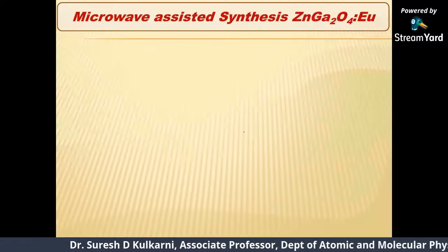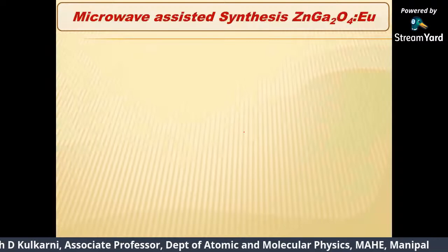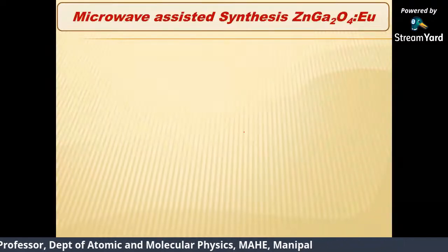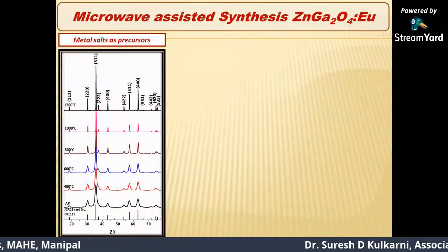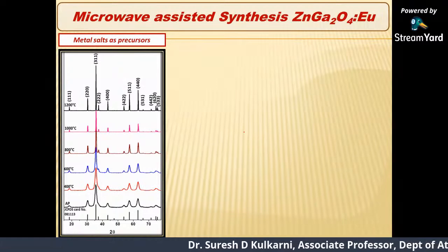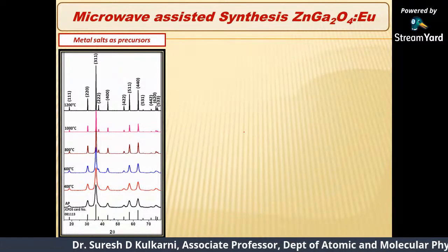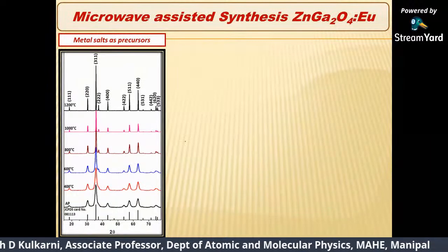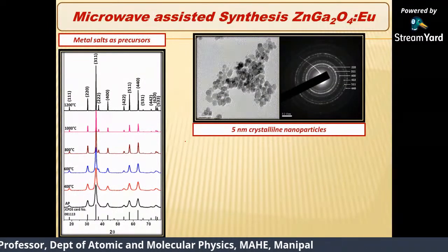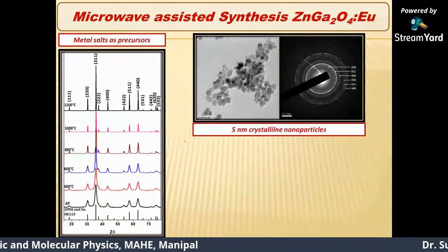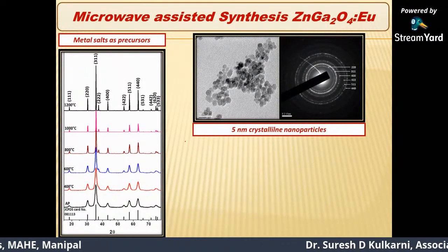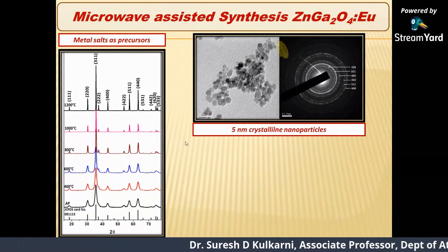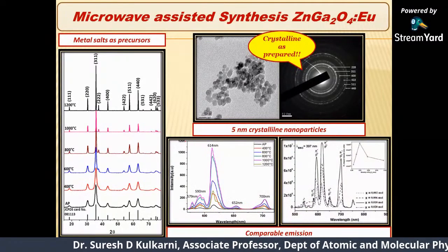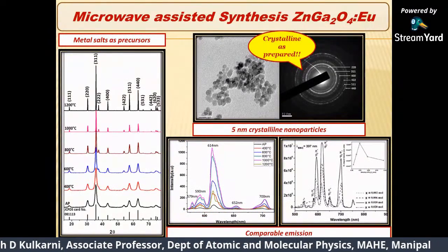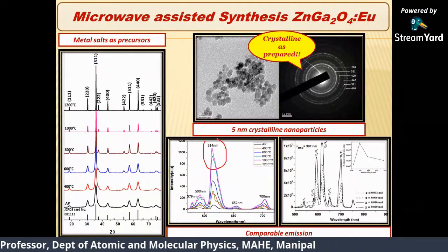This is a commercial red phosphor. In your televisions, the red color which is coming is because of the europium doped phosphors. This time, instead of metal organic precursors, we started using metal salts as precursors. With metal salts, you can see that the synthesis can be accomplished in a very quick time. And 5 nanometer spherical nanoparticles can be prepared. They are crystalline, and the material gives you predominant red emission at 614 nanometer.